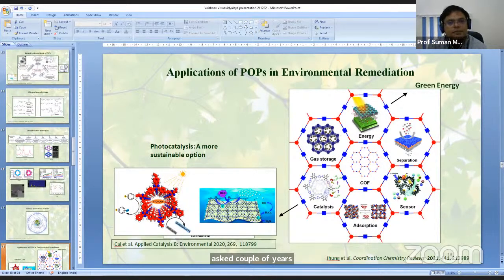We have synthesized one such polymeric porous compound by reaction between piperazine and some triazine linker. And we get a surface area of about 625 meters square per gram and a pore size of about 7.55 nanometer. What we find is that it can selectively capture mercury 2+ ion inside the cavity of our covalent organic framework. And the mercury capture can go up to 1329 milligram per gram from the Langmuir plot we obtained.